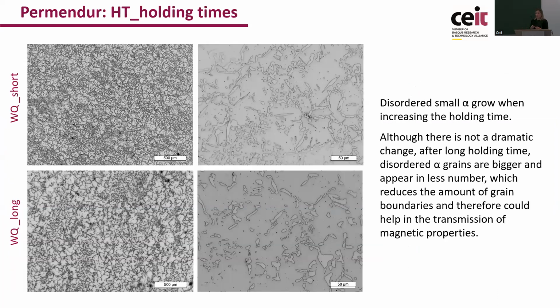In addition, we did another study in parallel where we were changing the holding times. And in here, what we wanted to find out was if we were able to increase the size of the alpha grains and reduce the amount of grain boundaries, whether it was possible to also increase the magnetic properties without reducing the mechanical properties. Although this is not so high a difference, it works, but it still needs the intermediate cooling rate.